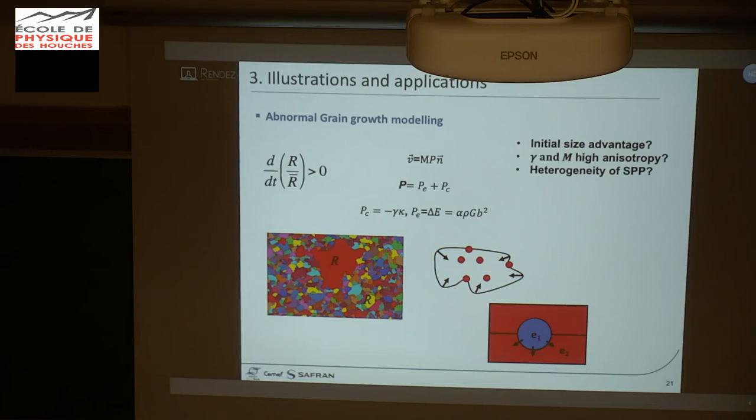And generally, if you go in the state of the art, you will see that this kind of phenomenon is explained by three main mechanisms. You can have some advantage of some grains at the beginning of the thermal treatment, what we call initial size advantage. You can also have some anisotropy of grain boundary energy and mobility, which can explain that one grain interface could be an advantage over the other grain interface. And you can also have some heterogeneity of second phase particle population.